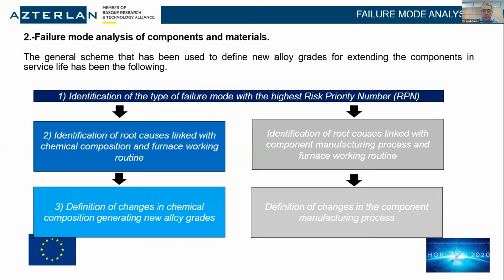In the case of the defect, if the root cause is linked with the chemical composition, we should define changes in chemical composition generating new alloy grades. Whereas in the other case, we would have just to adjust the process performance or change the process or make modifications in the process to avoid this failure mode taking place.